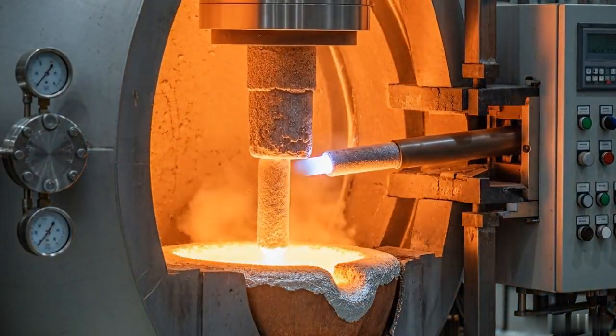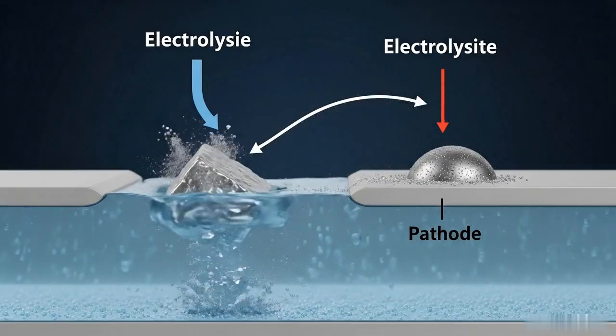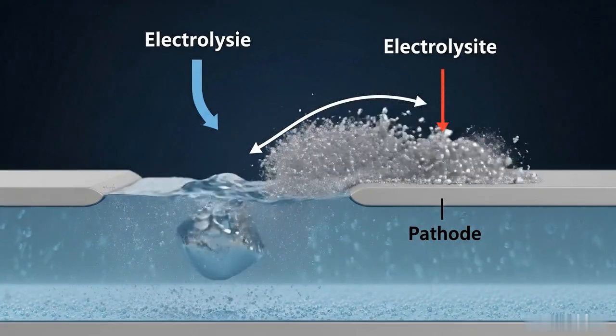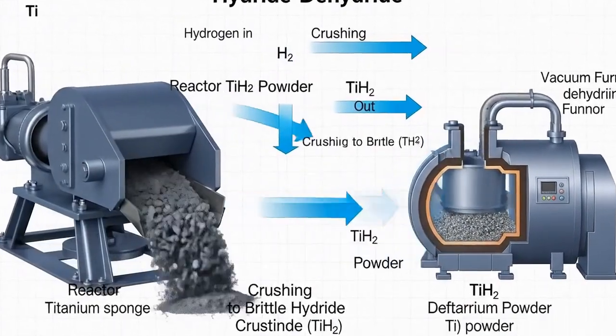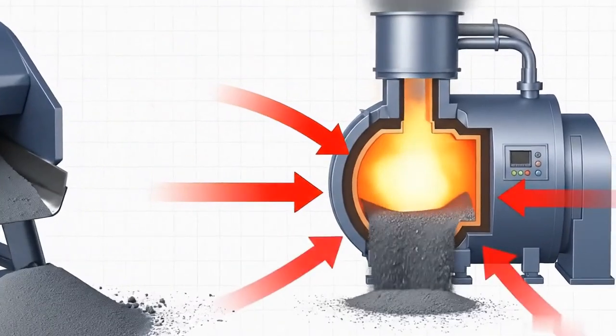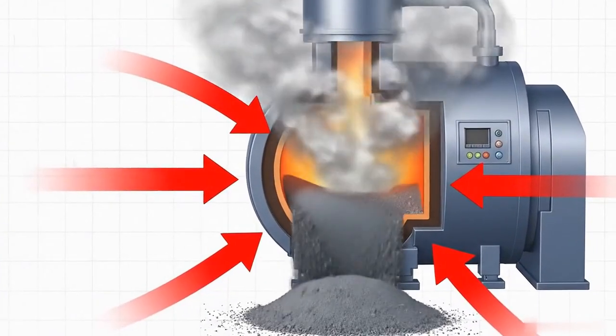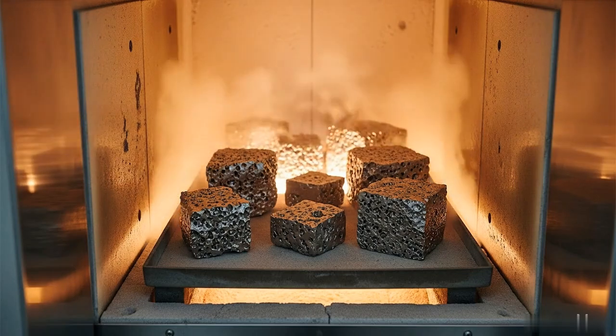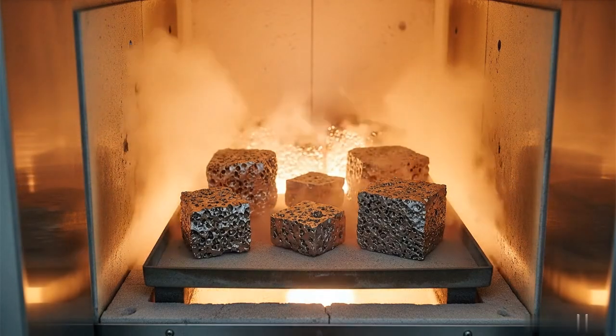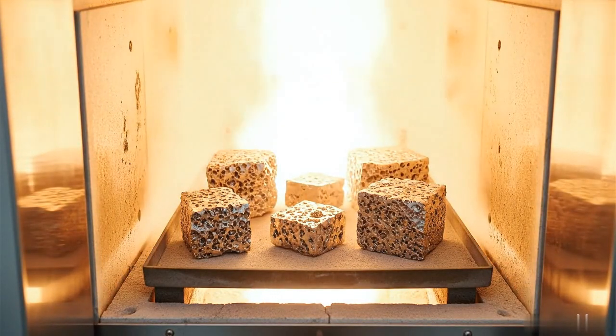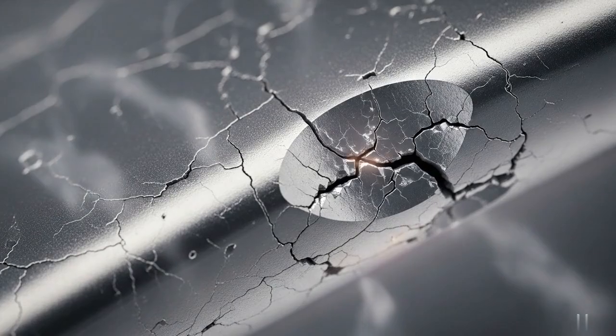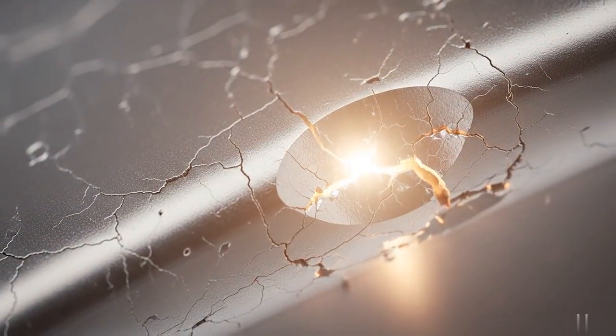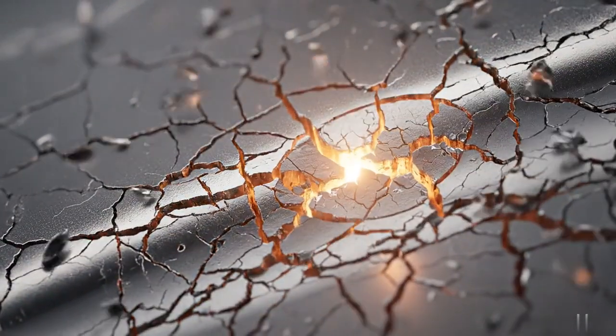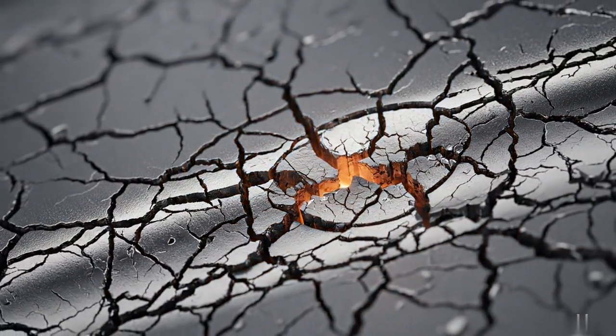In many factories, the ingot is then used as feedstock for powder production via several competing methods. The most common commercial route for titanium powder today is the Hydride-Dehydride process. In HDH, titanium sponge or scrap is placed in a hydrogen furnace and heated under hydrogen atmosphere. At temperatures around 400–600 degrees Celsius, titanium absorbs hydrogen and becomes brittle titanium hydride.